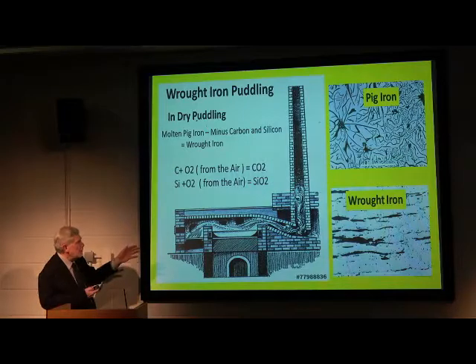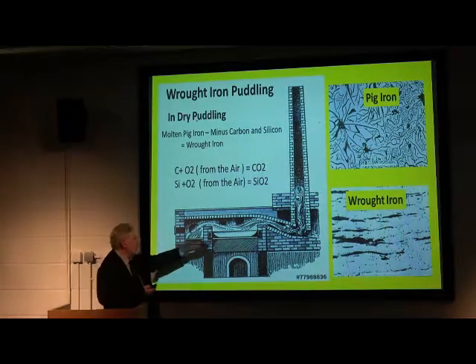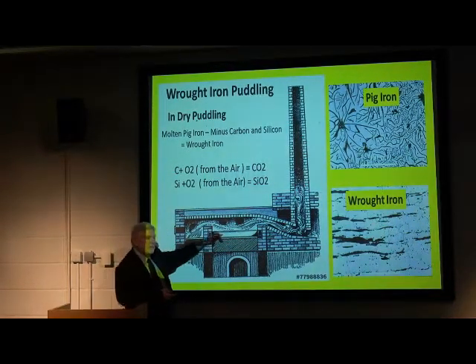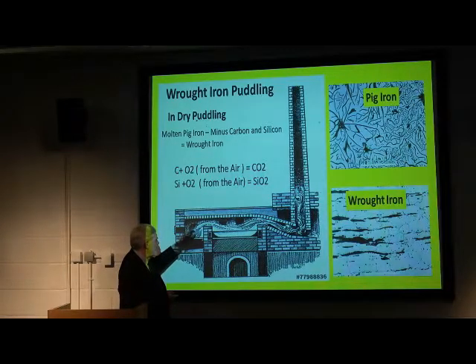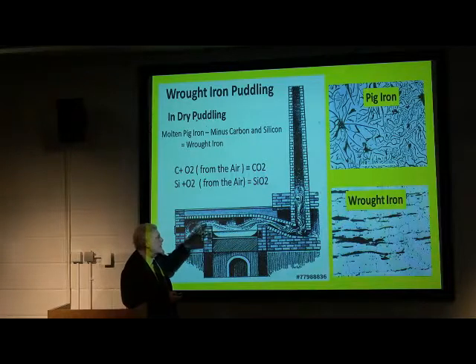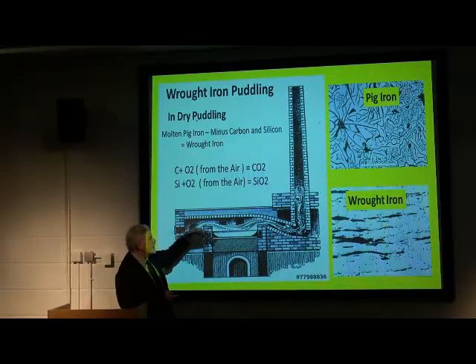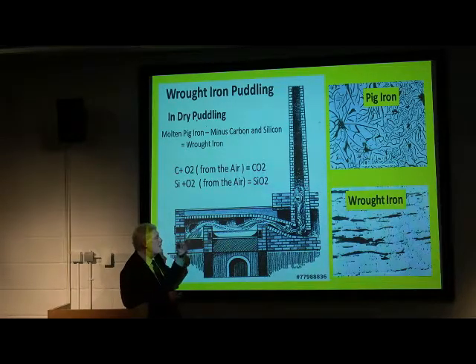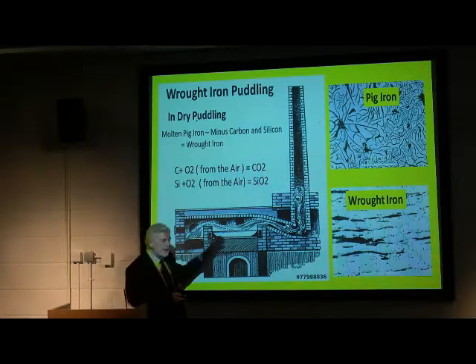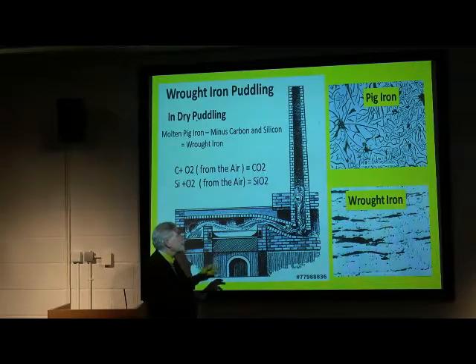Here we have the puddling furnace. You start off with molten pig iron here, and you put pigs of pig iron in. You have a fire going here. The fire has got a lot of excess air on it. It heats up the pig iron, melts it, and the air reacts with the carbon and the silicon in the iron to purify it. That's effectively the dry puddling process.